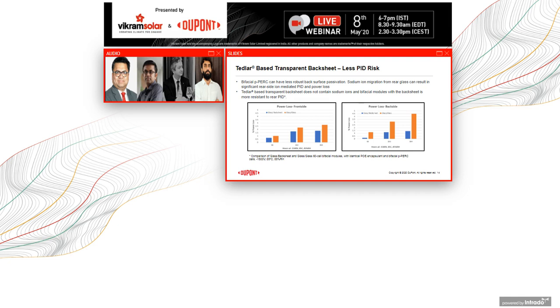Next, I'd like to show some results on PID, as was also mentioned by Ivan. Bifacial PERC cells, depending on the rear side passivation, if it's not optimized properly, can lead to losses in power. Showing here results from full-size commercial solar modules comparing glass and a transparent backsheet. More importantly, I would like to draw your attention to the rear side results, and we see clear differentiation all the way up to 384 hours. Mind you, this is again much more harsh than is required by any IEC or other accelerated tests.